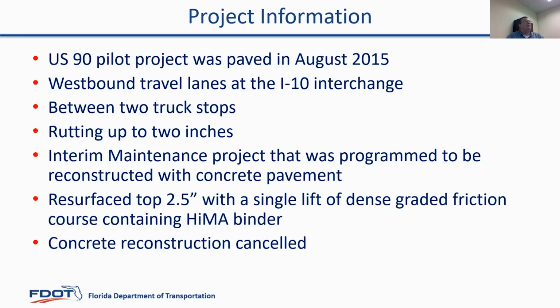So we only did it in the westbound travel lanes at the I-10 interchange there on US 90 between 2 truck stops. The district reported they had up to 2 inches of rutting. So they had programmed something that's going to make all the asphalt guys on the call there cringe. They programmed a concrete reconstruction project. But they needed to address the rutting in the interim. And so having learned of the high polymer research at NCAT, I believe Greg and the folks that were here at the time decided to try it on this project.